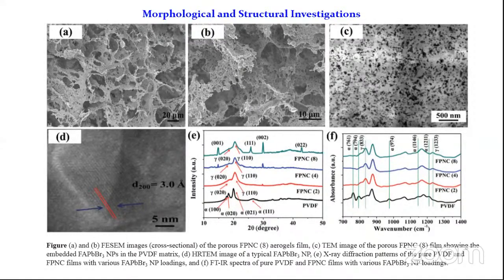This can also be proved from the TEM image, where all the formamidinium lead bromide nanoparticles are equally distributed throughout the matrix. The formation of formamidinium lead bromide can also be proved by the fringe pattern in the polymer nanocomposite. We have seen that the 3.0 angstrom is representing the 200 plane of the nanoparticles. The formation of gamma phase can also be proved from the FTIR and XRD analysis.